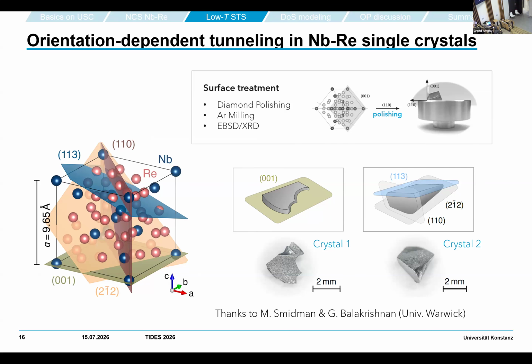And the 4 planes that we're probing are shown here in this graph. We were probing in the ground plane, the 001 plane. We were probing in this diagonal plane 110, and then also two other ones which are not parallel to any crystalline axis: the 2-minus-1-2, shown in yellow here, and the 113, shown in blue. And why were we probing these directions?